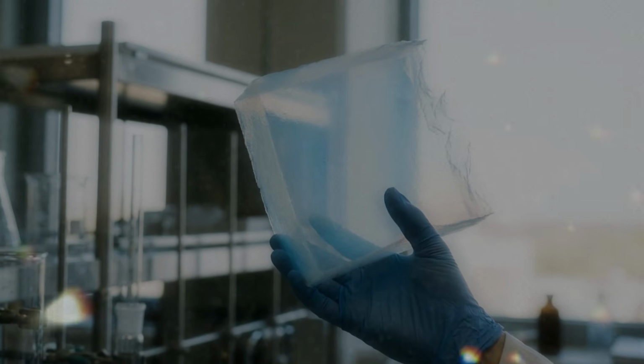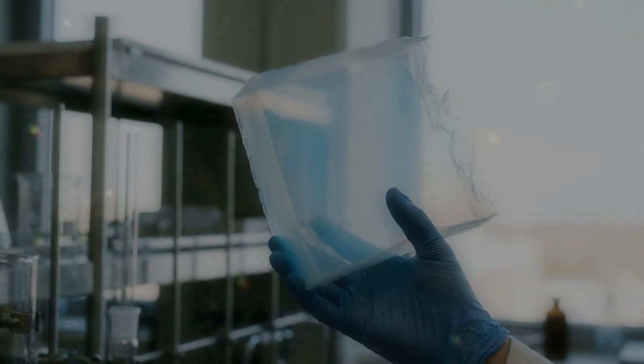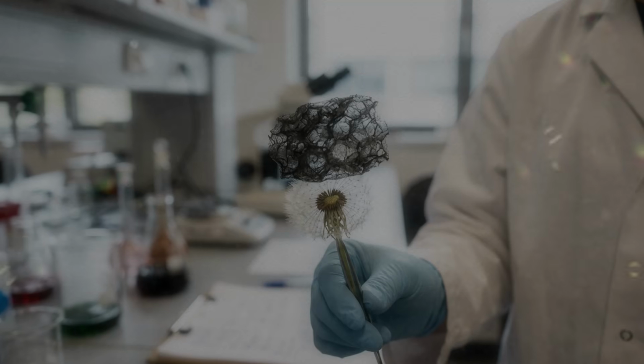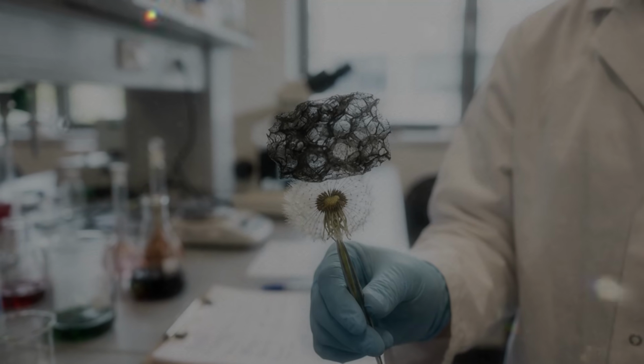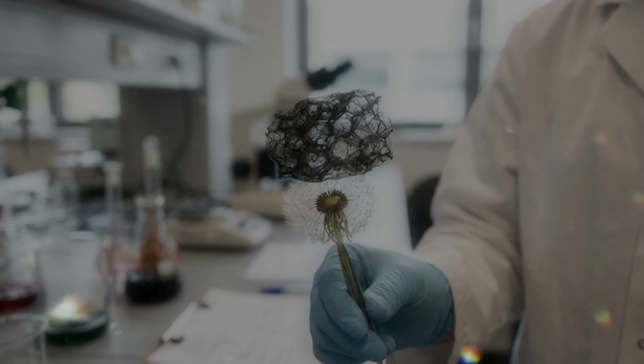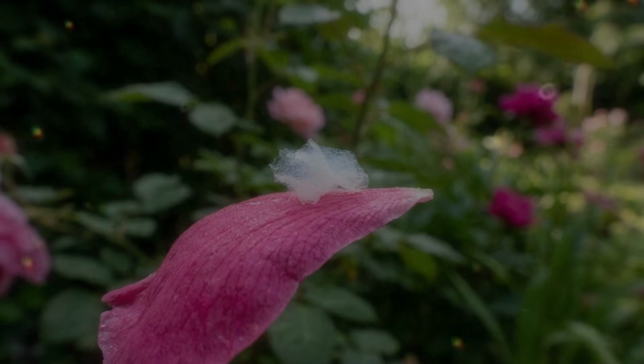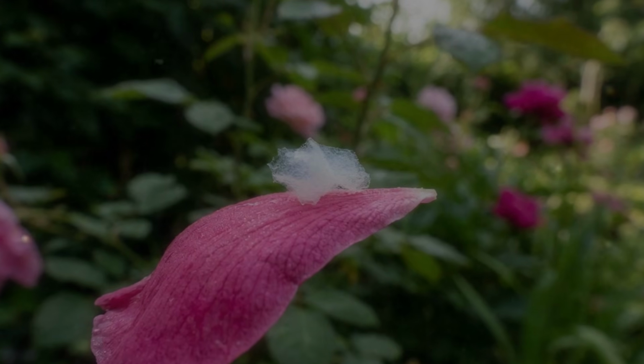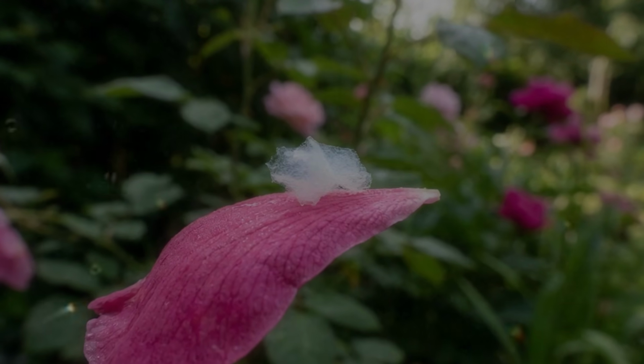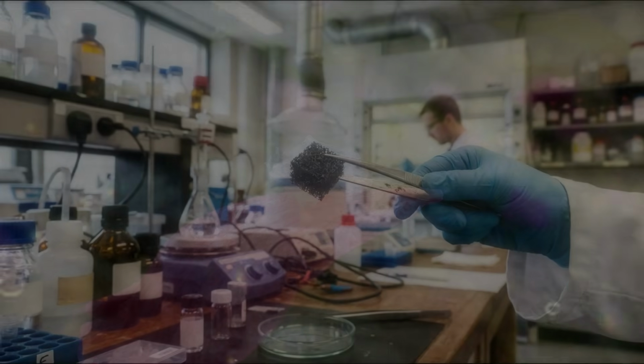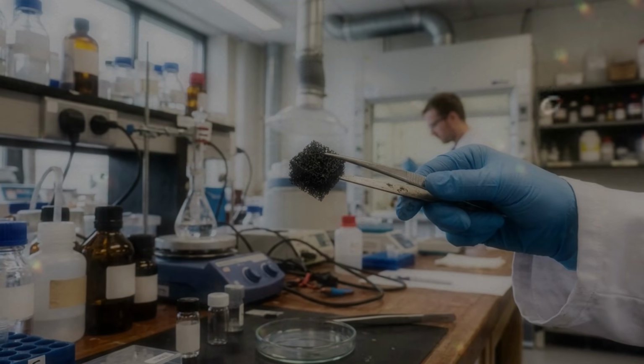Crystals grow inside the pores and can push the solid framework aside. Large crystals may produce large channels, while rapid freezing may create finer structures. The final material often has a different internal architecture from an aerogel made by supercritical drying. That difference can be useful.